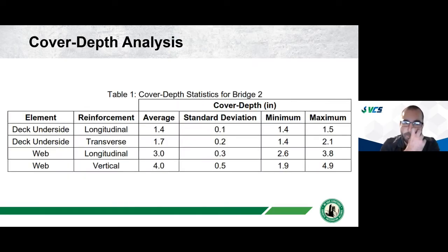And so, looking at the cover depth, we can see a lot of variation in the cover depth. And one of the big issues here is, we see in the vertical in the web, we see quite good cover depth, 3-4 inches of cover. But in the underside of the deck and other areas, we see the cover depth drop to 1.5 almost. And so in a chloride environment, that's a very low cover depth. And so certain areas of the structure which had lower cover depth than other areas put it at a more advanced risk for corrosion activity there.